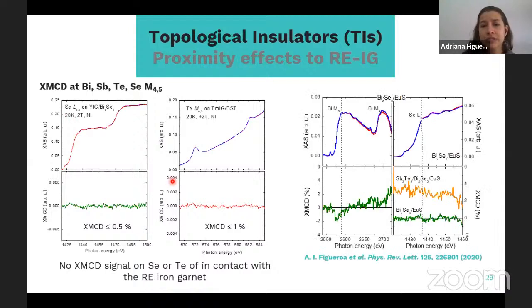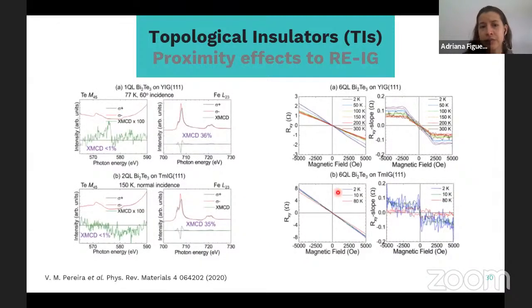And this is exactly what we found also for the europium sulfide, the other magnetic insulator. This behavior on iron garnets with XMCD has also been recently reported. But in that work, it's surprising that there's no XMCD, but there's still anomalous Hall effect. In magnetotransport measurements, you see some signatures of proximity effect. So it's important to understand what happens there. There's something at the interface that is not well understood, or that we're failing to understand and to control in these materials. So further investigation is needed.